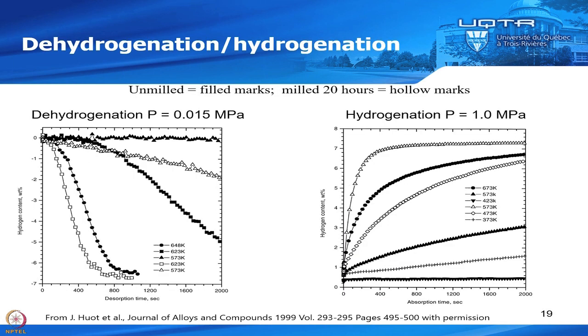So if we look at the dehydrogenation characteristics, this is the unmilled with the filled marks and the milled with the hollow marks. So this is the unmilled, this one, and this one. And you see, for example, at 573 K, the unmilled one is really not desorbing. It doesn't want to desorb, but at the same temperature, the milled one started to desorb.